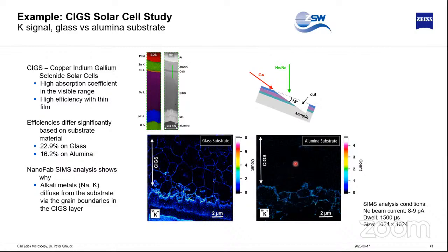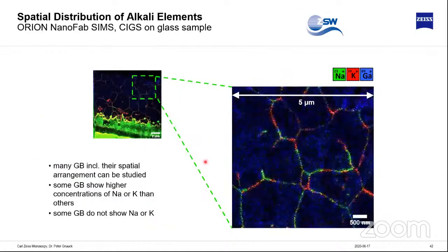We don't see anything in the grain boundary, so nothing migrates into the grain boundaries on the alumina substrate. And just to take that a little bit further, we can do a high resolution SIMS analysis of these grain boundaries, and then we see in green sodium, we see the potassium in red, and we see the gallium in the background here. So now I think this is a wonderful example that we can really do extreme high resolution nanoanalytics in grain boundaries in all kind of structures here.